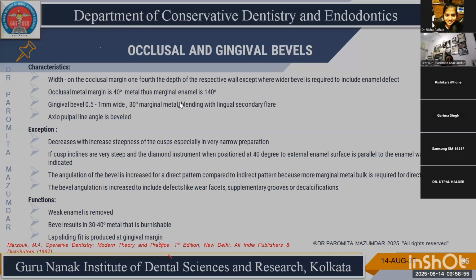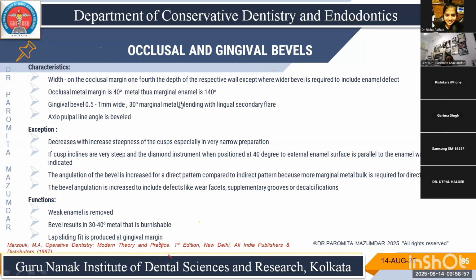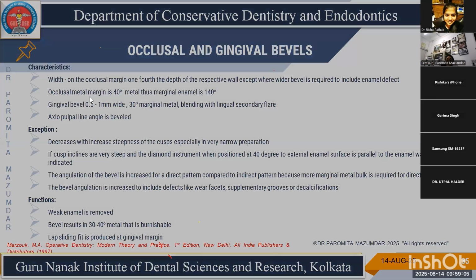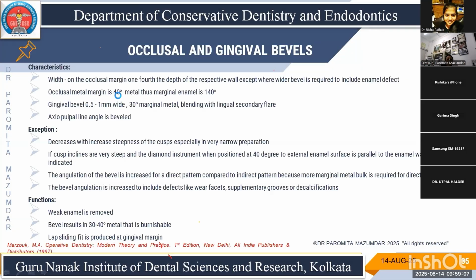Now, occlusal and gingival bevels are another very characteristic feature of cast restorations, especially when we are doing gold, because these create an occlusal metal margin of 40 degrees, making the marginal enamel 140 degrees. And the gingival bevel is usually 0.5 to 1 millimeter wide with a 30-degree marginal metal that blends with the secondary flare. We'll look at what the secondary flare is. This is just the occlusal architecture.